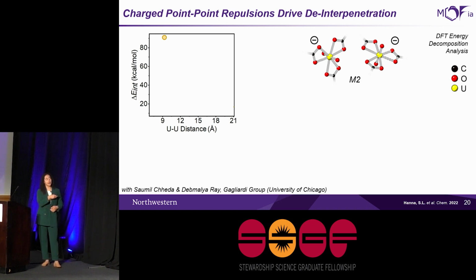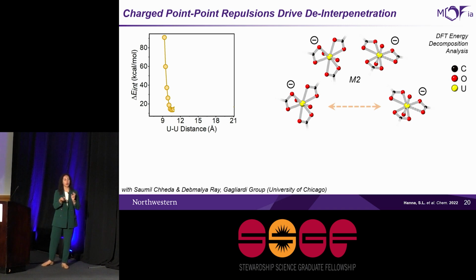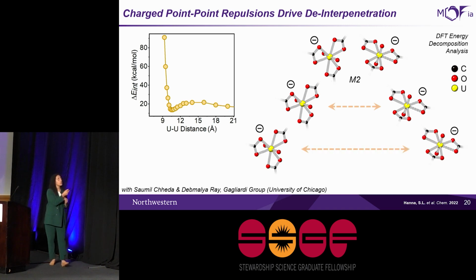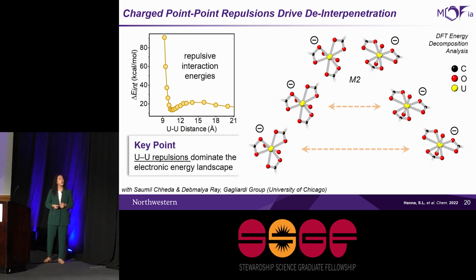And we did what's called an energy decomposition analysis, which is essentially where you take your motif here, your two different nodes, and you pull them apart. And as you pull them apart, you measure their interaction energy along this uranium-uranium distance. And here in the bottom of this well, you can see is the most favorable energy conformation. But what's really interesting here is that throughout this entire interaction energy diagram, you can see that all of the energies are positive, which means that they're all repulsive, really supporting the idea that these charged point-point repulsions are what's